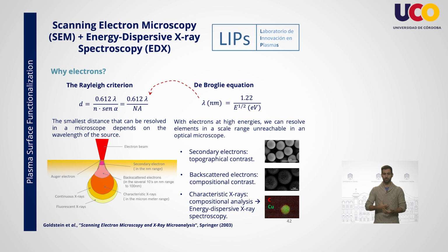When an electron beam impinges on a sample, it interacts with it, generating different types of signals. In an electron microscope, we have different detectors that collect these signals and transform them into usable information. Specifically, in a scanning electron microscope, we can use secondary electrons to obtain topographic contrast, while with backscattered electrons, we can measure compositional contrast. Furthermore, we can carry out localized compositional analysis using energy dispersive X-ray spectroscopy.